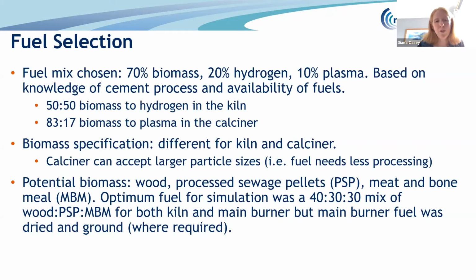So for the biomass, fuels with different physical properties were chosen for firing at the kiln and for the calciner. And the reason for the difference in physical properties is that the calciner is able to accept larger particle sizes or chips that require less processing effort, which in turn makes them a little cheaper and easier to access. The biomass chosen was a 40-30-30 mix of wood, processed sewage pellets and meat and bone meal. So that mix of 40-30-30 was the same for the calciner and the main burner, but the fuel for the main burner was further dried and ground before use.